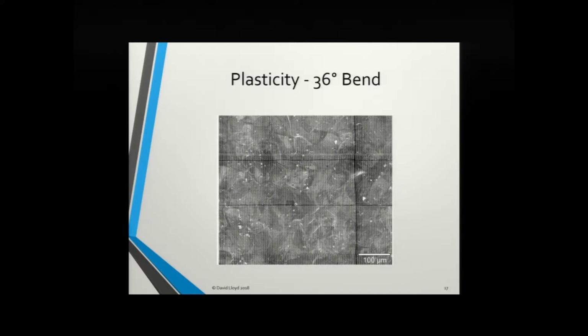And you can see this is only at a bend angle of 36 degrees. It's a very low bend angle. You can see some minor distortions in the grid, as you'd expect, but there are two things that jump out at you. One is, although you can't see it too well in this slide, you will see slip lines in the grains, and you'll also see these features. And these features are displacements at the grain boundaries. Remember now, we've got an upper bend surface. Essentially, the grains at the surface are totally unconstrained, and they displace. And it's not an insignificant displacement. And I'll show you in a minute.